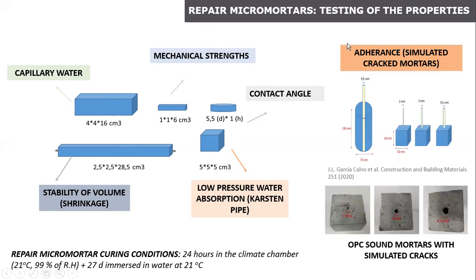We also have tested the adherence of these repair micromortars to the traditional OPC substrates, and for that we have prepared several types of standard mortars with simulated cracks with different thickness from 2 to 9.5 millimeters, and then we have sealed these cracks with selected previous repair micromortars.